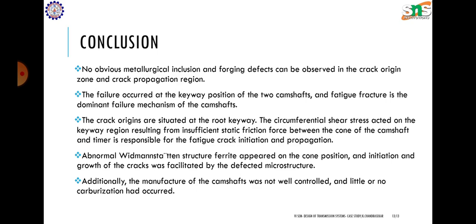No obvious metallurgical inclusions and forging defects can be observed in the crack origin zone and the crack propagation region. So there are no material issues or forging process issues which cause the fatigue failure.